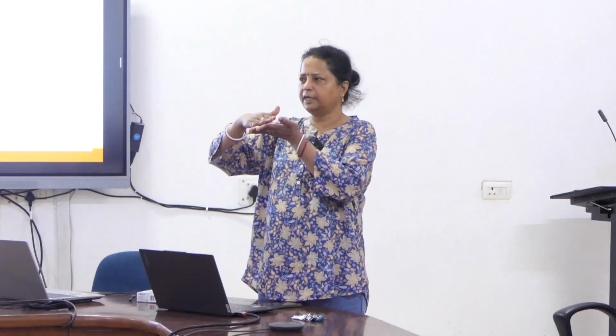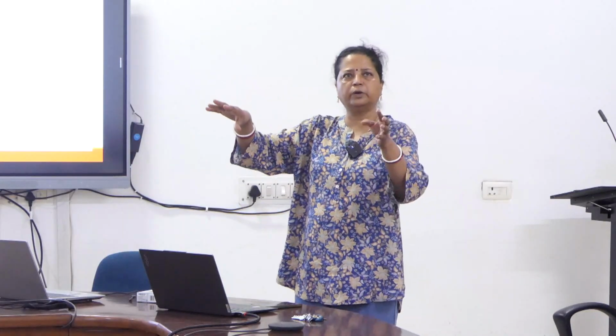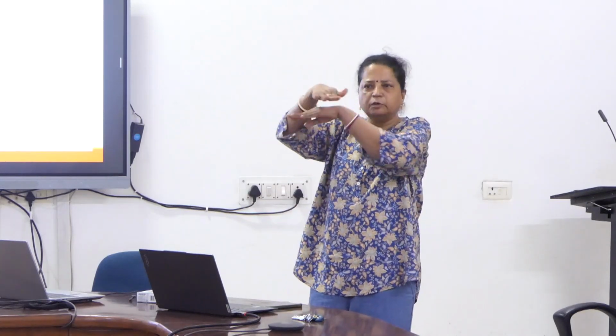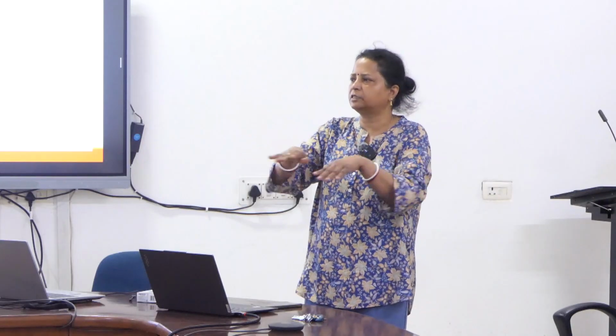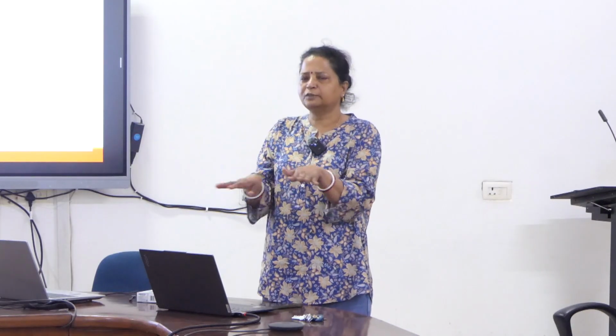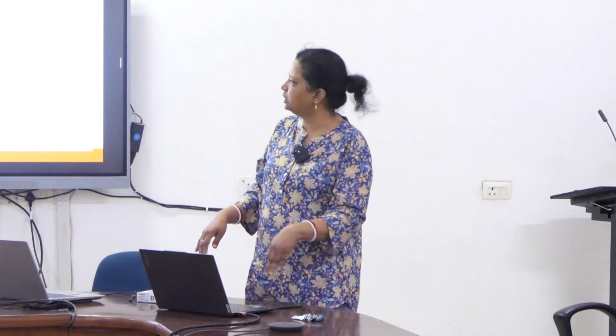The other thing is liquid phase exfoliation, where you do it with sonication, like when you have a graphene layer or any 2D material. So you have stacking, right? They are called van der Waals structures. Van der Waals bond means very loosely attached. So you have the layers one by one, and by sonication, ultrasonication, they will break after some time. So the liquid phase ultrasonication gives you the flakes, meaning single layers.